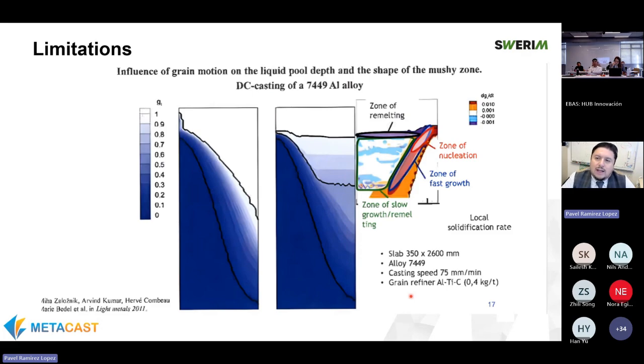Of course, it's harder to take into account grain motion, and that's why I take this publication as an example, because it's an effort to portray this grain motion and the transport of grains. As you saw in the previous videos, the actual transport of grains can also act as nucleation sites when you break off a dendrite arm, for example, and it becomes a nucleus for a new grain, and so on. So portraying this is actually very challenging in a deterministic model.